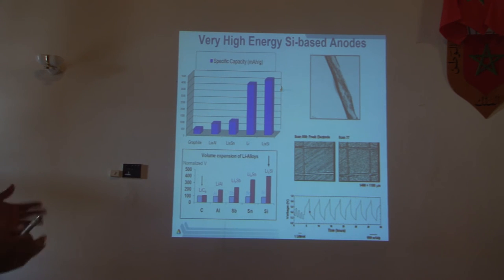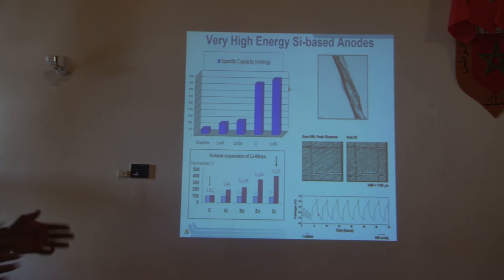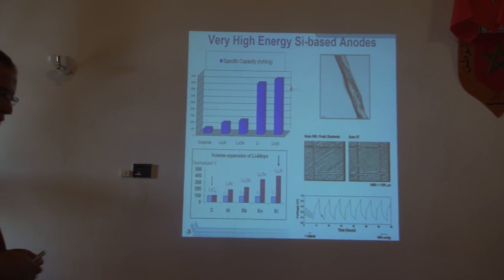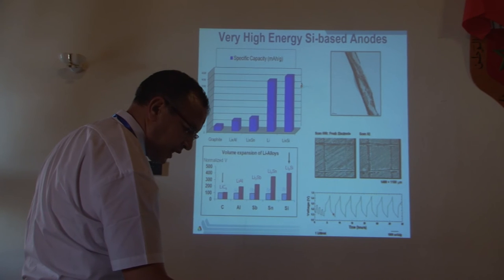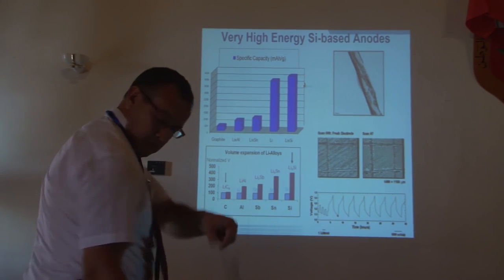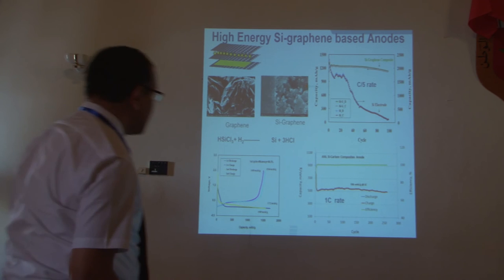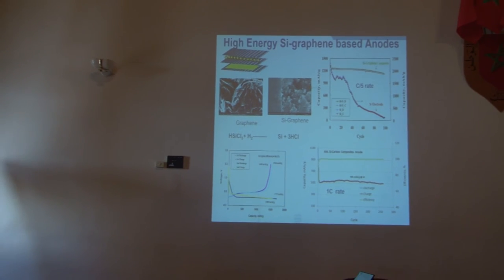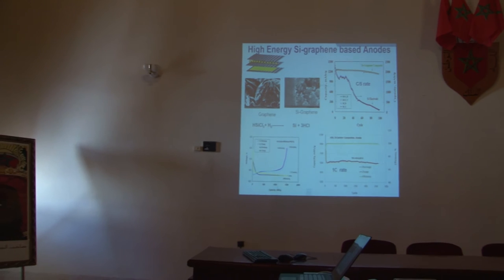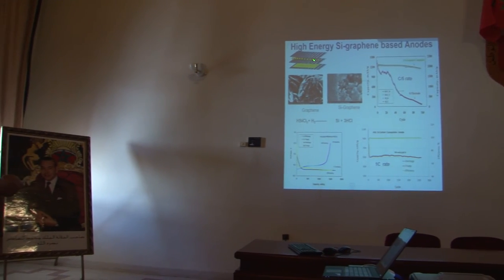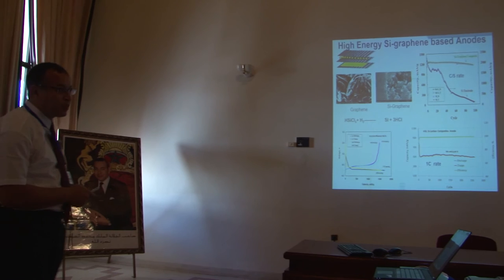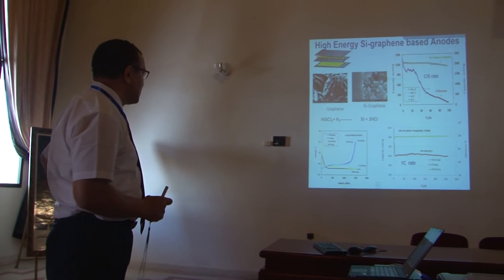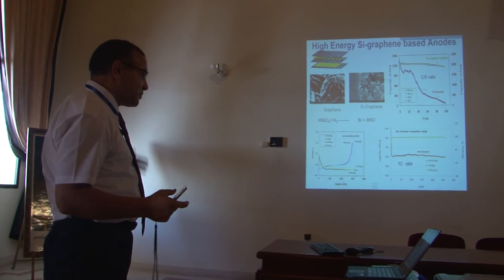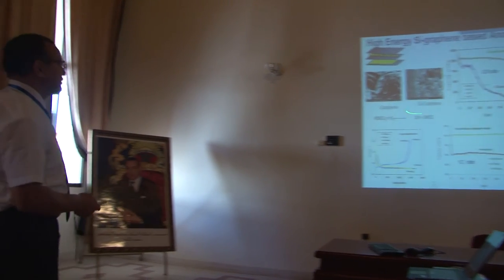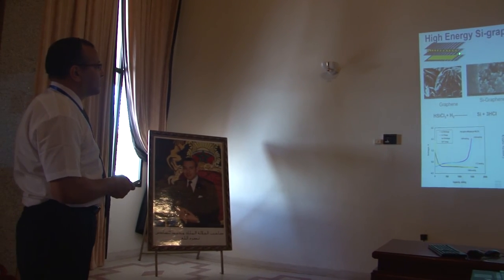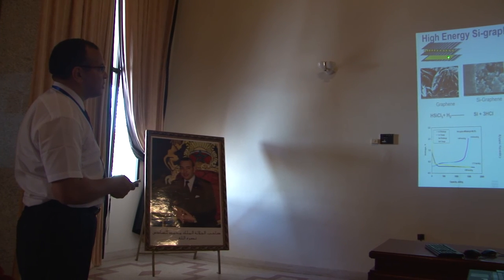The concern is that after several cycles, some of these particles will be totally isolated. Therefore there is no current moving and they become completely inactive. At Argonne, we're looking at ways of keeping the conductivity and preventing isolation. Here is a way which is very interesting. We developed a process which is based on a byproduct of the semiconductor business. It's mass produced because the folks have it there and they don't know what to do with it. So what you do basically is incorporate silicon between graphene sheets.